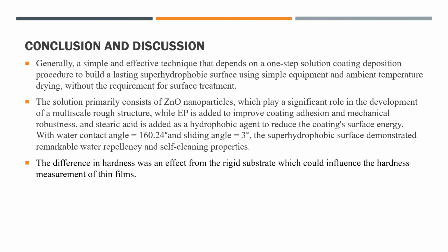For the conclusion and discussion, generally, a simple and effective technique that depends on a one-step solution coating deposition procedure to build a lasting superhydrophobic surface using simple equipment and ambient temperature drying without the requirement for surface treatment. The solution primarily consists of zinc oxide nanoparticles, which play a significant role in the development of a multi-scale rough structure, while epoxy is added to improve coating adhesion and mechanical robustness, and stearic acid is added as a hydrophobic agent to reduce coating surface energy, with water contact angle 160.24 degrees and sliding angle at 3 degrees. The superhydrophobic surface demonstrated remarkable water repellency and self-cleaning properties.